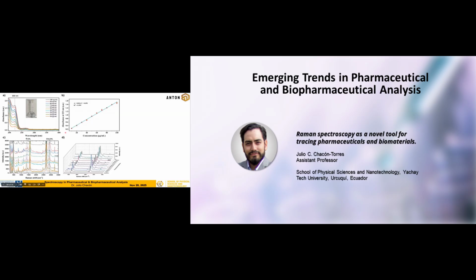What happened when we made the analysis of the Raman spectra? Our pristine graphene is the lower peak that we observe here. It's not so clear because we overlaid one on top of the other, but we immediately observe that additional peaks arise not only in the D-G region, but also in the 2D region, and they are extremely strong and clear to be observed. We immediately assign those peaks in the high frequency region to the CH2 and CH3 molecular vibrations of the molecule that we were studying, in this case ibuprofen for this graph.